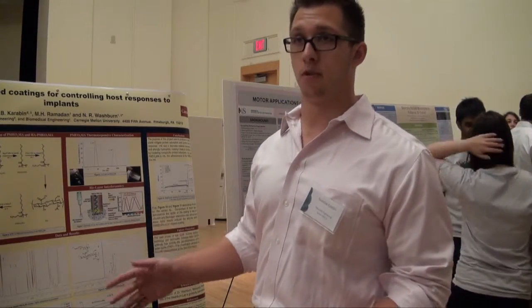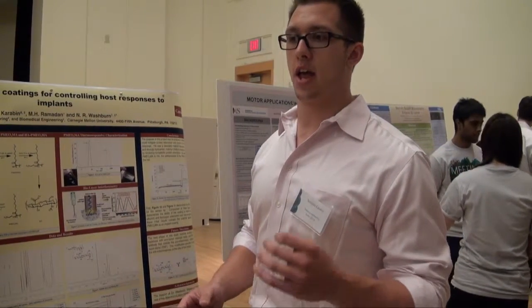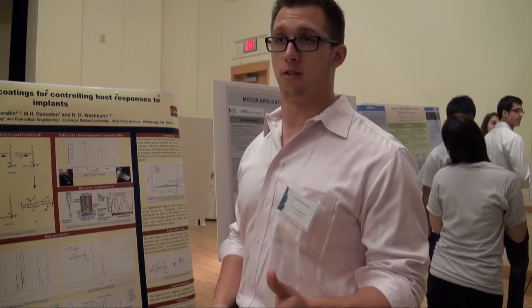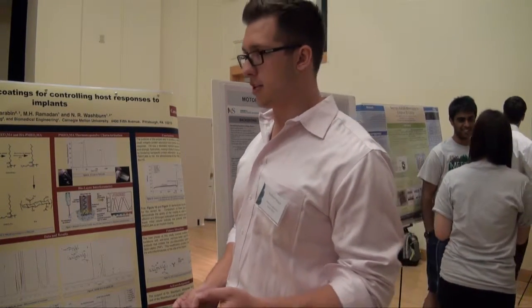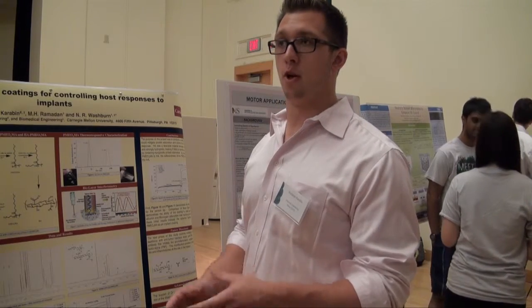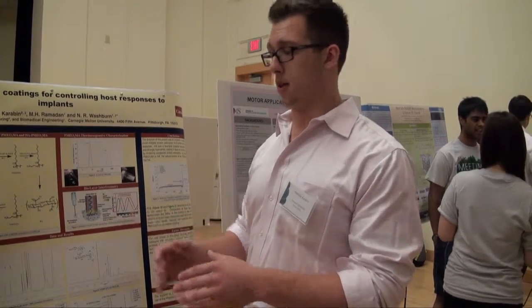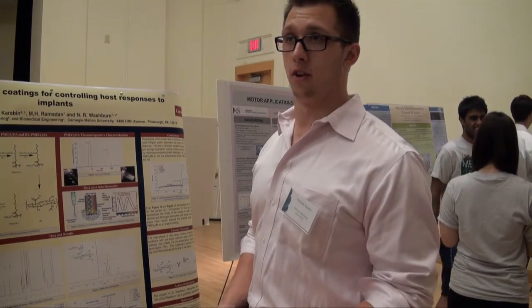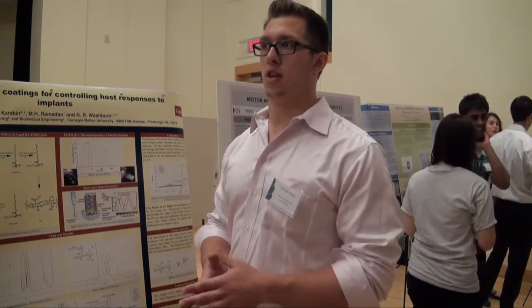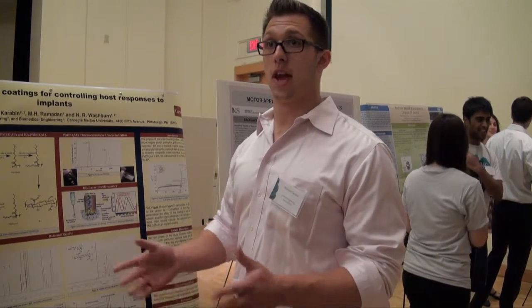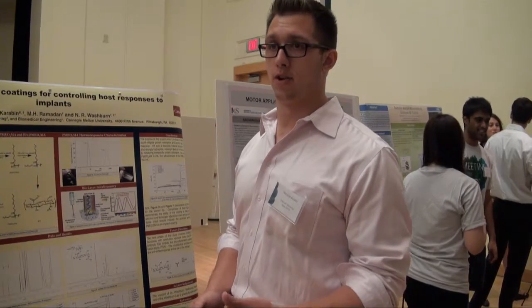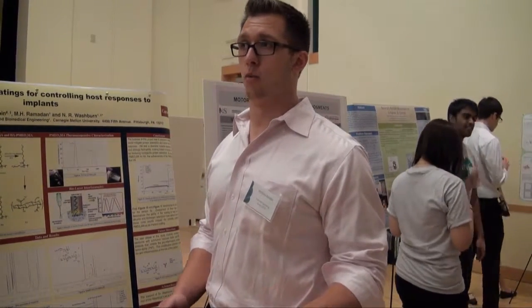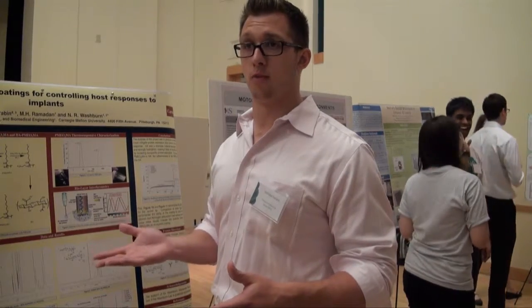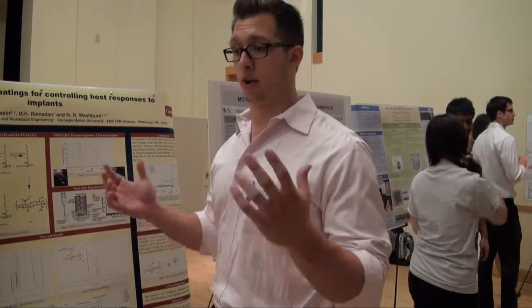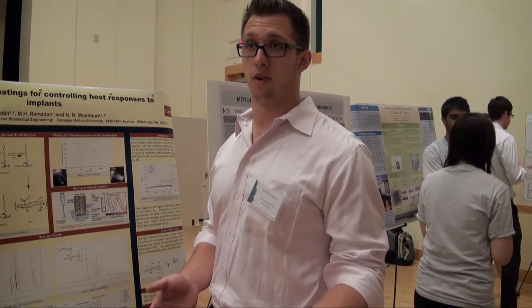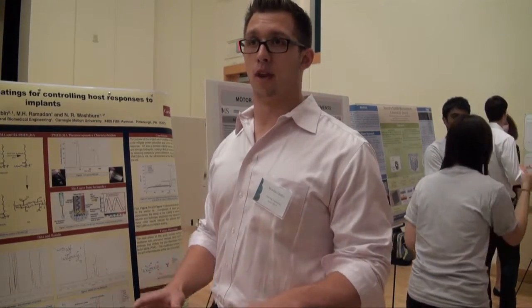Number two, it's temperature responsive. There's a term known as the LCST, the lower critical solution temperature, which is the temperature that represents when this polymer in solution is going to act in a single phase or in a binary phase. For this polymer, the LCST is 26 degrees Celsius. So this allows the HA polymer solution to be injected into the patient non-invasively and as a liquid. And then once the human body increases the temperature of the polymer to 37 degrees Celsius, that polymer is going to crash out of solution because its LCST is 26. That's going to allow it to coat that implant rather evenly, non-invasively.